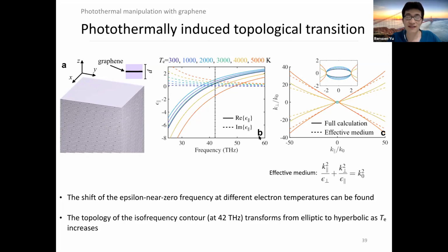And more interestingly, when we increase the temperature, we can shift the epsilon equal to 0 frequency from lower frequency to higher frequency. And by doing so, when we look at one specific frequency here, about 42 terahertz, we can see that we can control the isofrequency contour at this particular frequency by simply heating graphene. And the isofrequency contour changes from elliptic shape to hyperbolic shape when we increase the temperature.